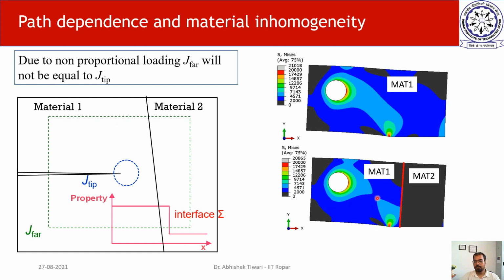In such scenario, you look at this picture, is that now you see that the stress distribution is asymmetric, and for the same amount of J far, I will have more energy available at the crack tip because here there is no energy. So because the stress is zero, the strains are also smaller, so you can imagine the strain energy density to be very small here. So therefore more energy will be available on this crack tip, and therefore the crack will have higher tendency to grow. And reverse would happen if I change the material 2.